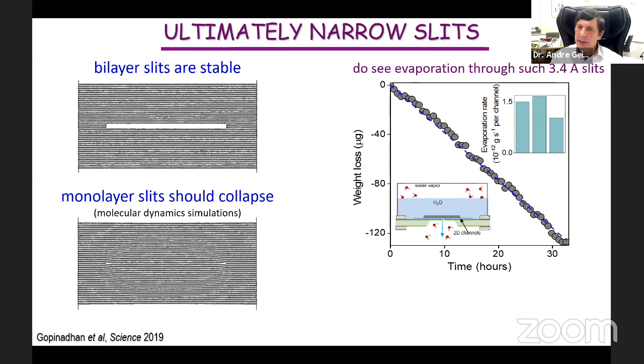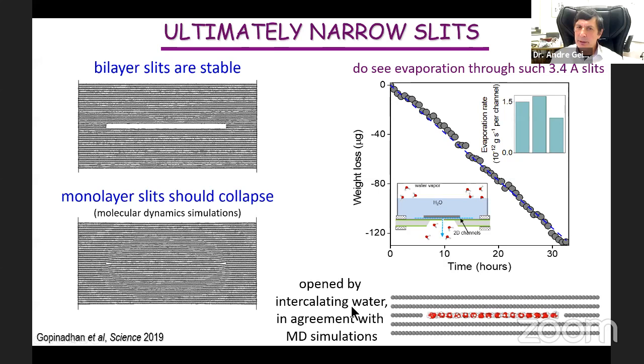What's happening? Why does theory predict that there would be no transport, but experimentally we do see transport? We believe what's happening is that initially capillaries are indeed collapsed, but when they put water around, those water molecules intercalate somewhere here and open those channels, and then water can go through. And when we do this molecular simulation in the presence of water, we do see that the channels become open. Intercalation of graphite, as you see in this case, happens with water molecules.